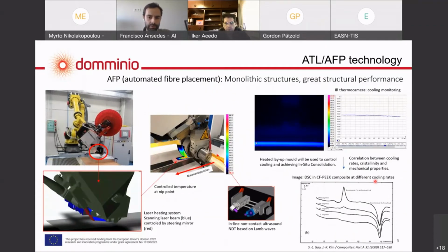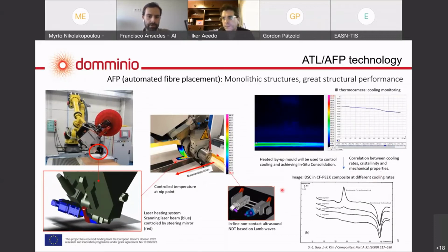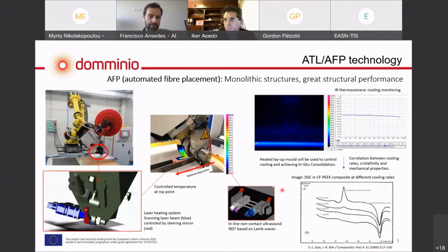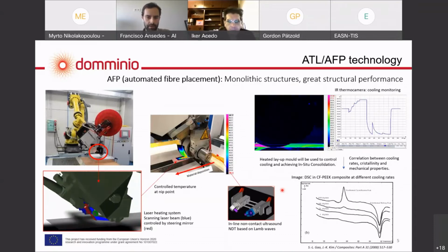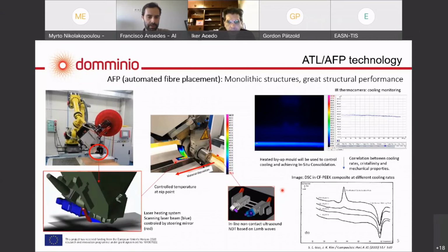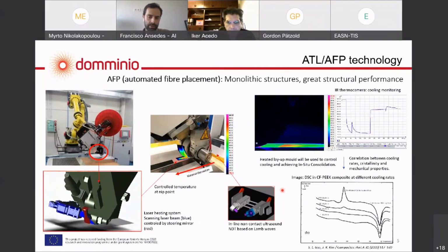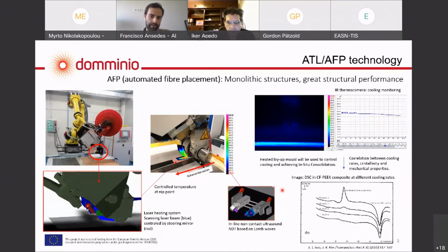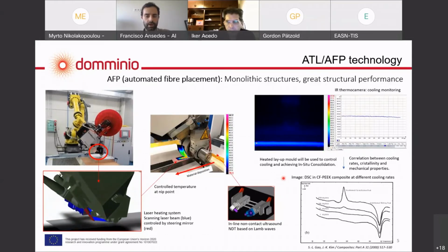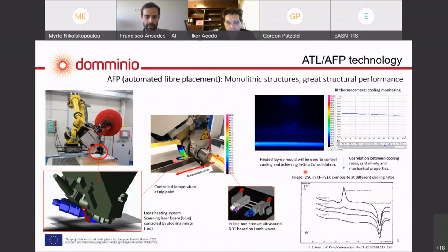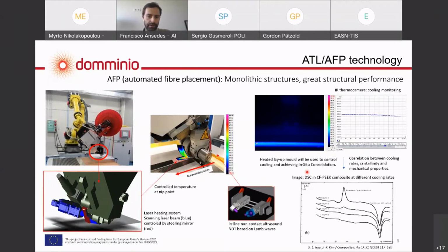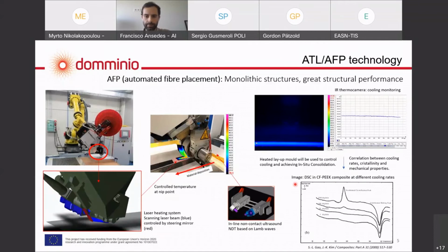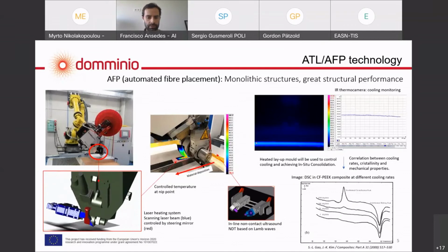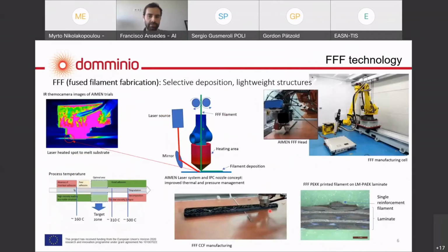This is in order to assure that we obtain a good consolidation between the tapes that we place and the substrate, to achieve in situ consolidation, that is, to have a finished structure at the time we finish the layup. So every ply that we apply is a finished part, and we don't have to undergo an autoclave cycle after this. To achieve this, we will be controlling the temperature by the laser heating and the heated layup mold. So this was an overview of the AFP technology, and we can go now to the FFF technology.